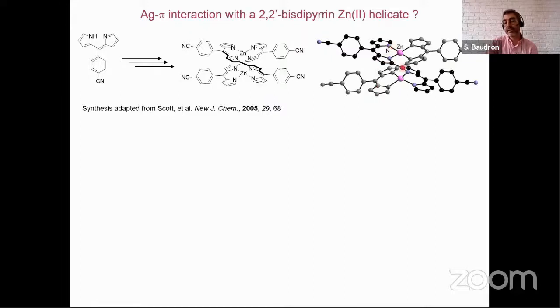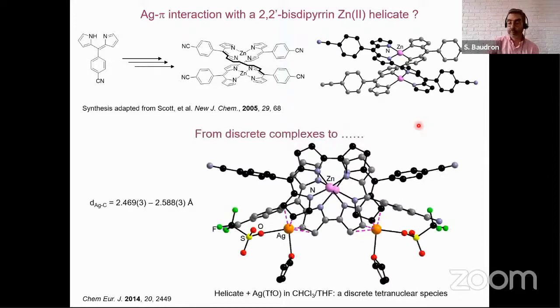And you see here the organization of the 2 strands around the 2 zinc cations. We then studied its assembly with silver 1 cation, and we observed that indeed the silver 1 cation is being complexed by the helicate, with a silver 1 sitting between 2 pyrrolic systems as we had hoped and anticipated. Interestingly here, the peripheral nitrogens are not completely in the coordination sphere of the silver 1 cation. It is the triflate anion and the THF solvent molecules from the crystallization system that complete the coordination sphere.